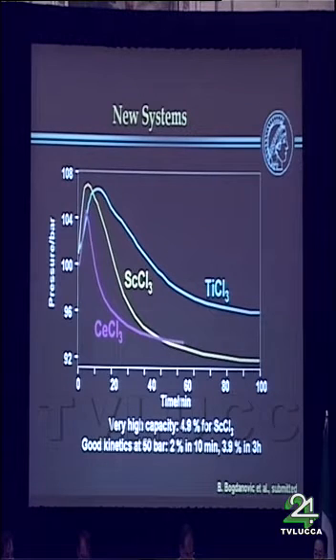And then kinetics for most of the materials reported are very, very slow. For the scandium and cerium-based materials, we have 2% storage capacity at 50 bars in about 10 minutes. And if you wait 3 hours, you again approach the theoretical capacity. So there is really room for improvement towards the low-pressure rehydrogenation with these materials.